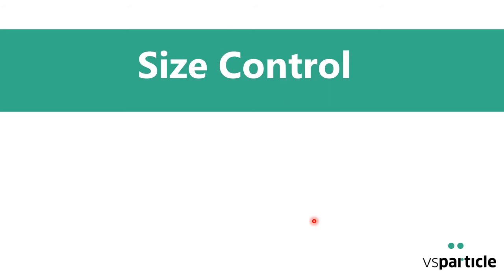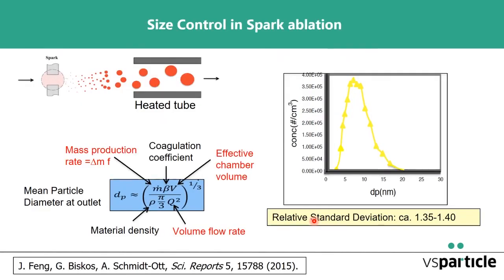Now, one thing we would like to do is, of course, control the size of the particles, and this is rather simple. Some time ago, we derived a simple formula that gives us an estimate of the particle size under the condition that the particles are nicely coalesced, which they do automatically in the beginning. And if you want to avoid agglomerates with fractal-like structures, you can heat the extension of the exit tube to a certain temperature where you know that this coalescence further occurs. So if the particles are more or less spherical, you can apply this equation to estimate the mean particle size that you get.